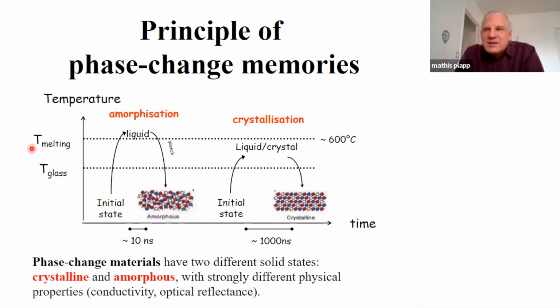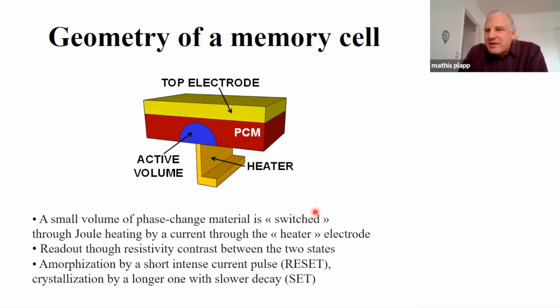And as many other materials, such phase change materials are in principle glasses. So you can control the state in which they end up by the velocity of the quench. This is symbolized in this graph, where on the y-axis you have temperature and on the x-axis you have time. If you heat them up by a very short and intense pulse, such that they get over their melting temperature, and then you quench them down quite rapidly, then they become amorphous. And if, on the contrary, you heat them up a little bit more slowly to a lower peak temperature and then let them cool down more slowly, then they have time to crystallize and they will end up in a crystalline state.